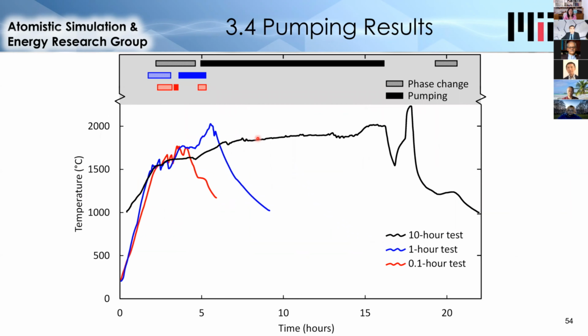Overall, silicon was pumped in 3 experiments over different durations: just a few minutes when the pump shaft got stuck, about an hour, where this test was ended because silicon leaked out of the tank for an unrelated issue from a design change, and finally 10 hours. At the top of this figure shown in gray are the phases of the experiment. So first we have shown in this hashed color the phase change time, and this is when the silicon is melting and then later when it freezes.